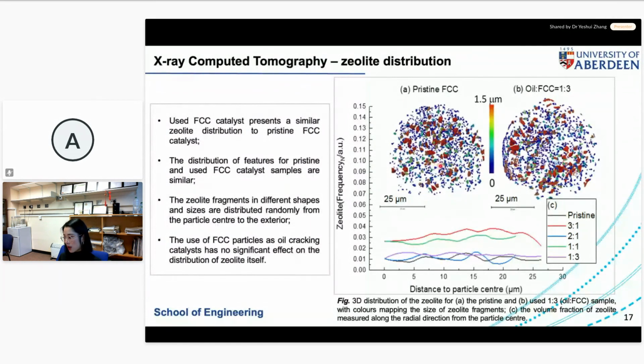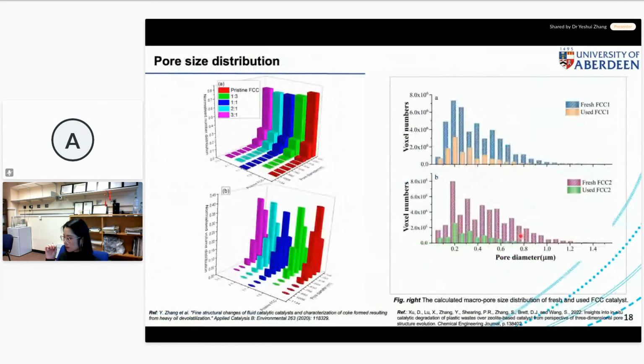We do have random sizes of this zeolite fragment, and we can also quantify the distributions of this zeolite throughout one particle. So that's actually a quantitative result we can extract from this X-ray nano CT. What else we can do with these X-ray CT results is the pore distribution.